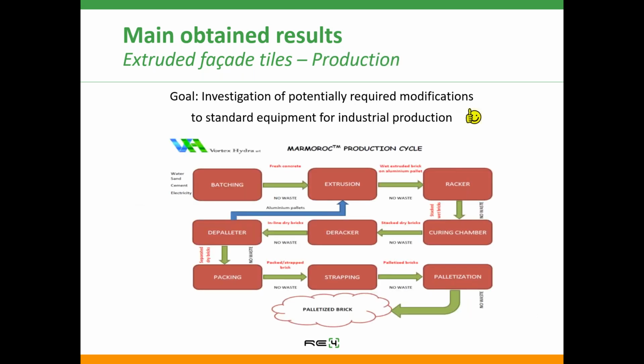It was very interesting that during the tests we have carried out, and also using the experience developed along the years of working in this field, it was really interesting to see that no upgrade or specific modification was required by the standard equipment to process the material with CDW aggregates. So basically, in an industrial scaled up plant, we can have a batching plant, usually working with a planetary mixer, because it's the one which grants the better homogeneity and better mixing. Then the fresh concrete is conveyed to the extruder, where the extrusion takes place.